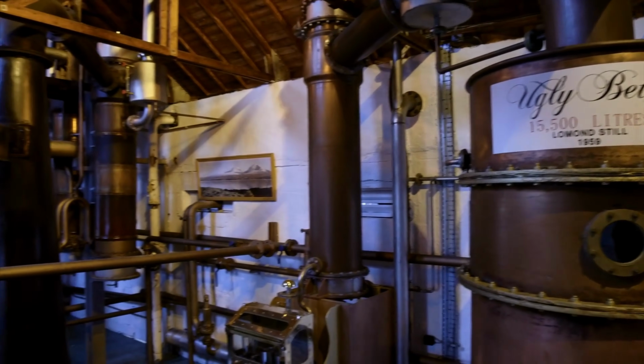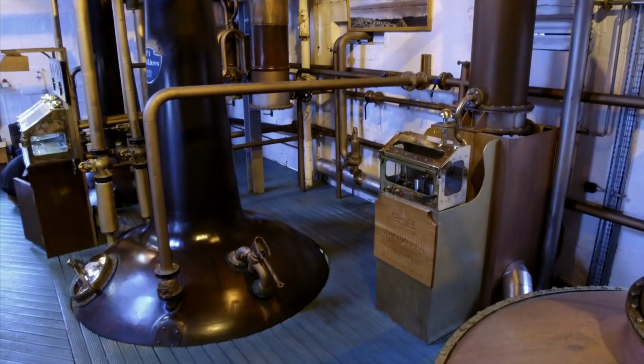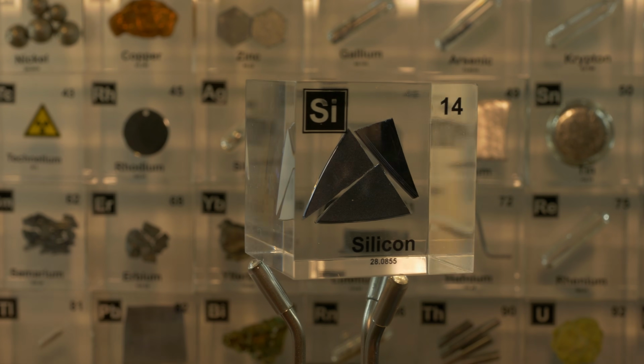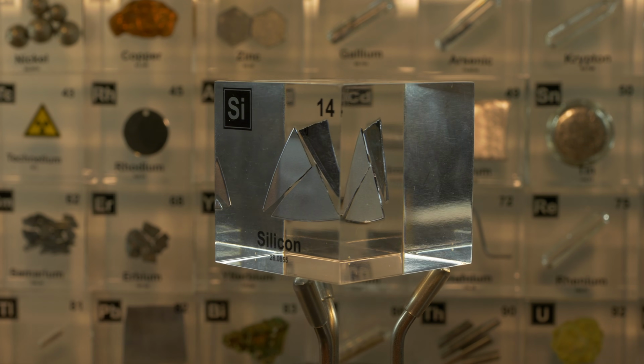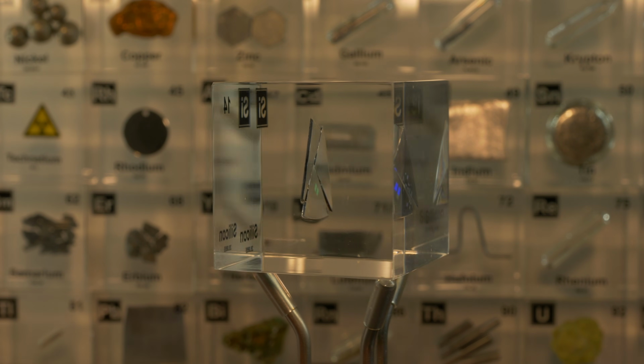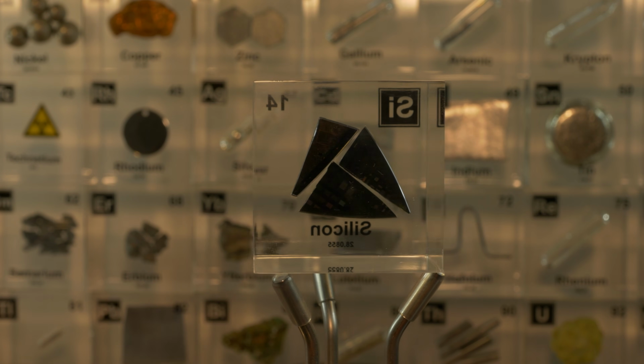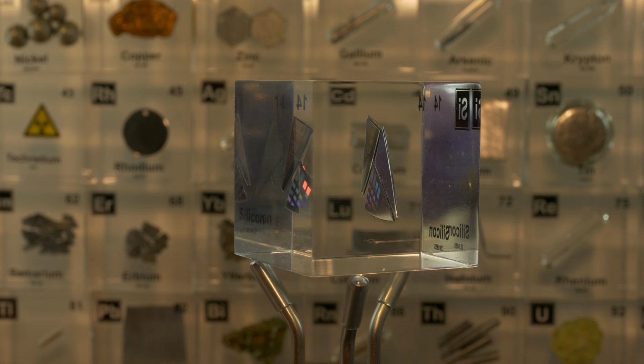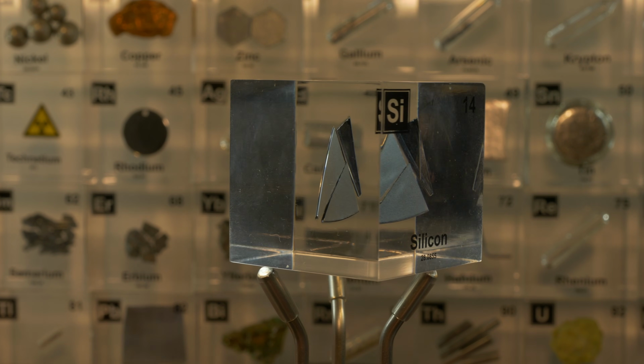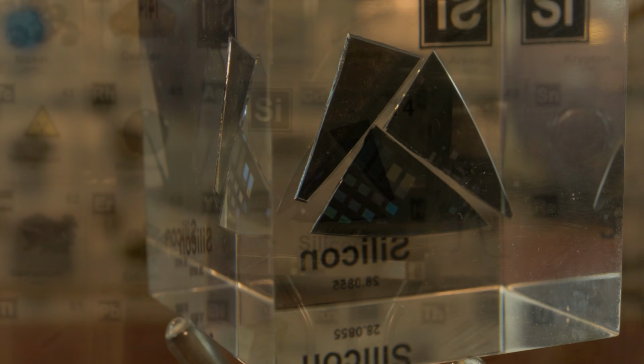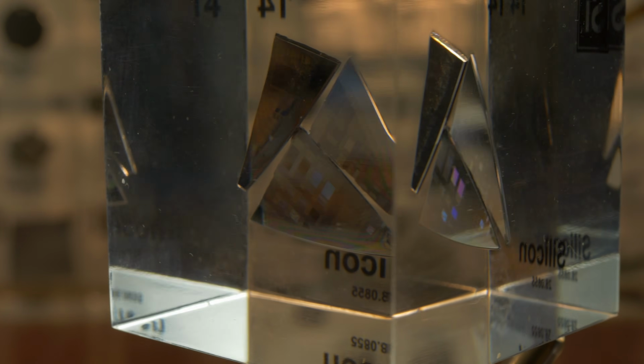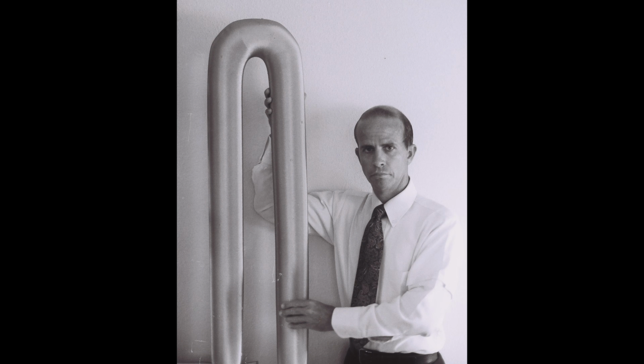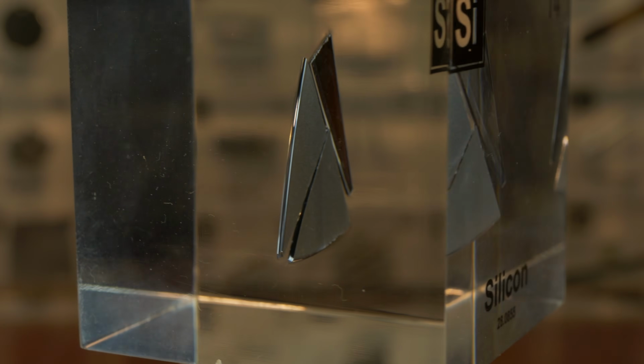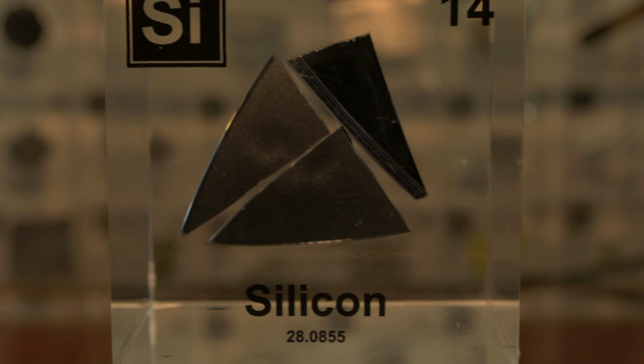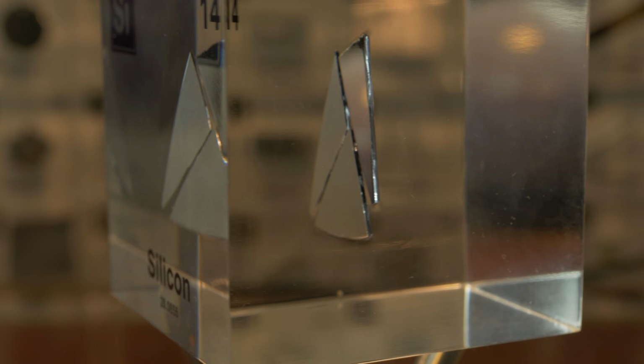Imagine vaporizing the silicon into a chemical form and then distilling it like purifying alcohol, only instead of whiskey you're distilling silicon juice. After multiple rounds of fractional distillation, you get extremely pure tetrachloride or trichlorosilane. Next, you convert those purified chlorosilanes back into elemental silicon. One way is to react trichlorosilane with hydrogen gas at high temperature on a silicon filament. Another way mentioned in some processes is reducing silicon tetrachloride with zinc vapor. Either way, the chlorosilane is decomposed and pure silicon is deposited, typically in the form of polycrystalline rods or chunks. The pure product is often called polycrystalline silicon, or poly-Si, and it looks like shiny crystalline chunks or rods. At this point, its purity is extremely high, like six nines or better. This poly-Si is the raw material for making silicon wafers.